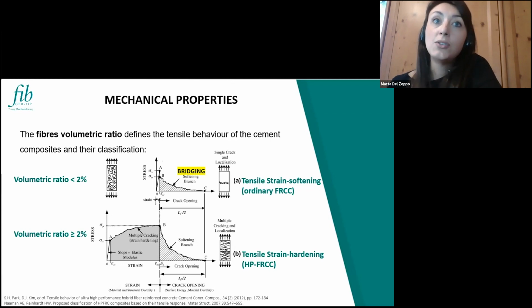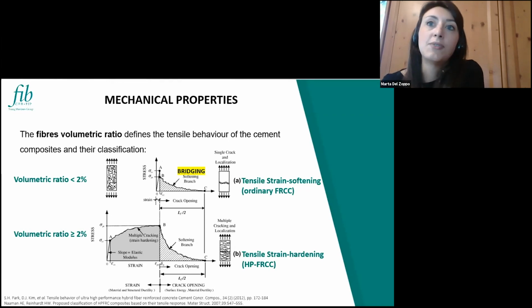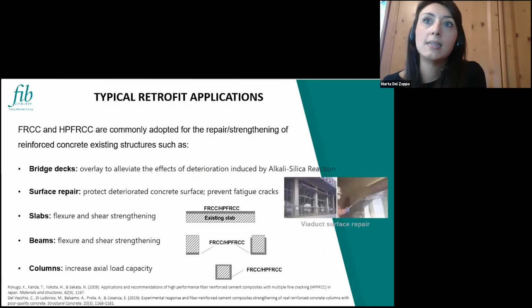But when the volumetric ratio of fibers is higher than 2%, we will have a different approach. During the tensile test, we will have the development of multiple macro cracks, like shown in this picture. So differently from the previous case, we will have multiple cracks and a strain hardening behavior. After the achievement of the first crack, we will have an increasing tensile capacity until the achievement of the maximum tensile capacity of the material, and then we will have again the strain softening behavior up to failure. In this case, these materials are called strain hardening, and they are classified as high performance fiber reinforced cementitious composites.